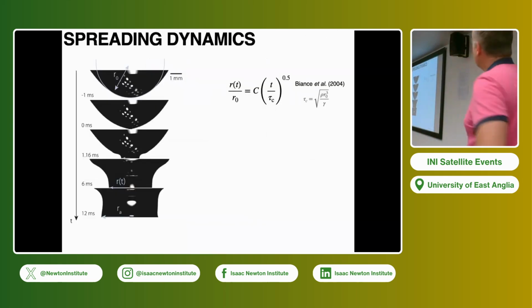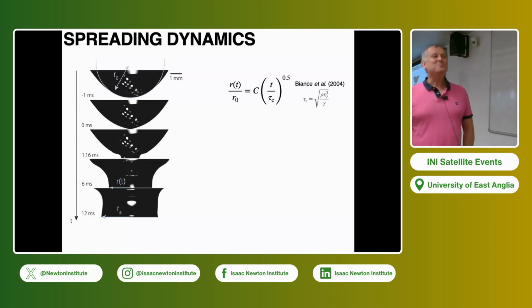Okay, so we use a work from, I don't know, 20 years ago now, about the spreading of a drop at the contact of, in her case, wetting surfaces. When the drop is just in contact with the surface, because of surface tension you want to expand, and what balances this extension? This is the inertia at first, if you neglect viscosity. If you just make the balance between surface tension that wants to pull the contact line, and inertia that is slowing down the dynamics, you get the scaling that the radius of the contact line as a function of time should go like the square root of time, and you can rescale that with the inertia capillary time.